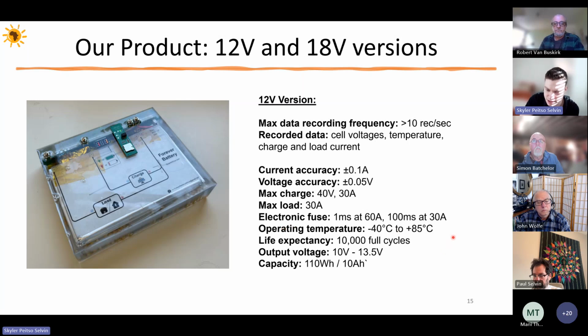And we expect it to last the full 10,000 cycles rated for the LTO cells, because we have these electronics and this protection system that will take care of the cells, keeping them exactly as they want to be within the correct voltage range. And the total capacity for this 5-cell version, or the 12-volt version, is about 110 watt hours. And we also have an 18-volt version, which is 8 cells in series.